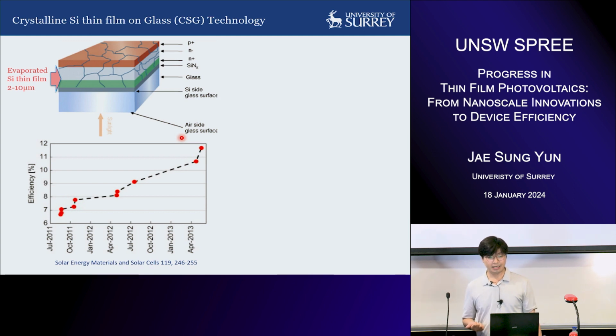Back then, I started working on crystalline silicon thin film on glass. This technology is not of much interest these days, and we worked hard to push the efficiency. The concept was to propose that we can make a thinner and cheaper silicon wafer that can be deposited onto the glass substrate. You can see that the efficiency went up to around 12% by 2013. But as you've seen in the previous slide, the cost of the silicon solar cell has gone down much.